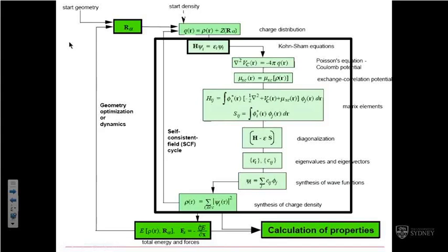You recalculate the electron density again, and calculate the force again. If there's still a force, you keep moving the atom until the forces are below a threshold. Okay. So with this approach, you can relax the position of the geometry of your materials.